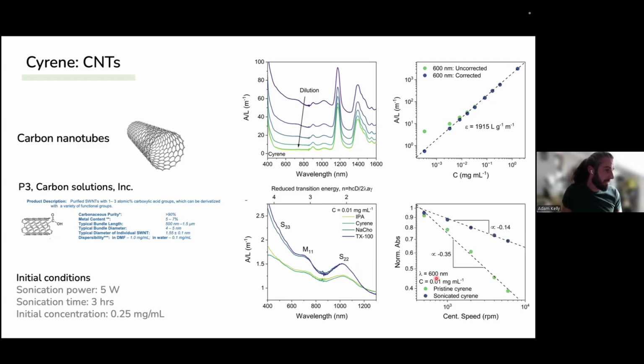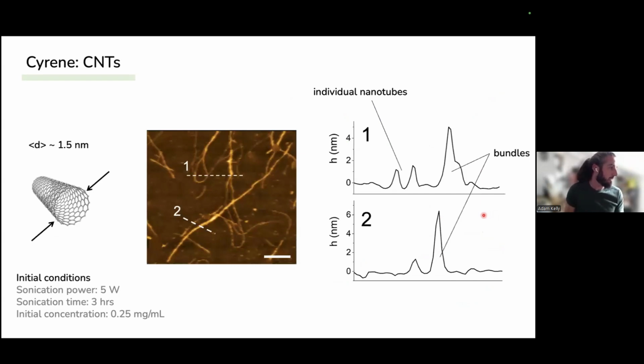Interestingly, if we centrifuge our material in just pristine cyrene here, it falls off at an exponent of minus 0.35. And if we disperse the same amount of nanotubes in the sonicated cyrene with the self-aldol condensate in there, it's actually more stable. So that dissolved solid appears to be conferring some sort of improved stability to the carbon nanotubes.